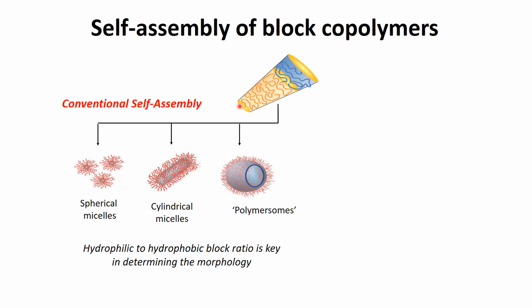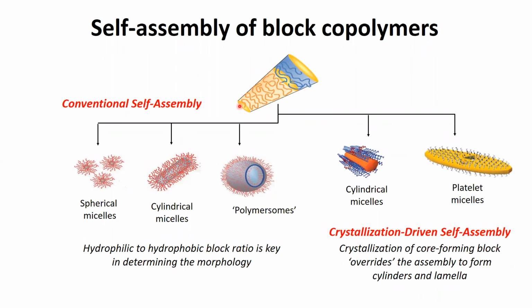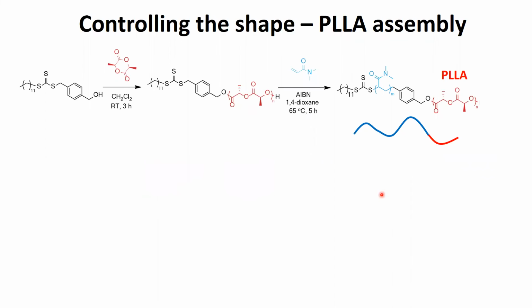That's very well established. The really interesting thing with polylactide is that because the red block is semi-crystalline, we can use crystallization methods to start to form some really interesting and quite different shapes. And that's what we want to try and do. And polylactide is a very simple, sustainable polymer, but the stereochemistry allows us to access some really quite interesting and strange shapes.